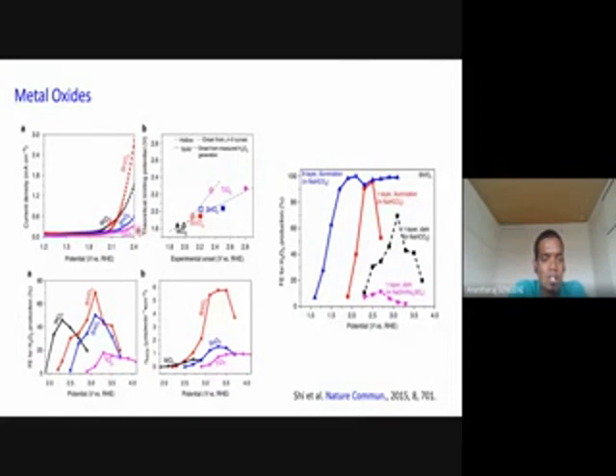And with bismuth vanadate, they have seen a Faradaic efficiency of 70%. I have told that Faradaic efficiency is nothing but the selectivity. So for hydrogen peroxide evolution, this particular material showed 70% Faradaic efficiency at 3.1 volt, which is very good, which was never observed before in water oxidation electrocatalysis. But when they applied photons, like they illuminated with light, they also saw a lowering in potential with the help of photons from an artificial solar simulator, and they observed very good Faradaic efficiency. The Faradaic efficiency is as high as 100%.